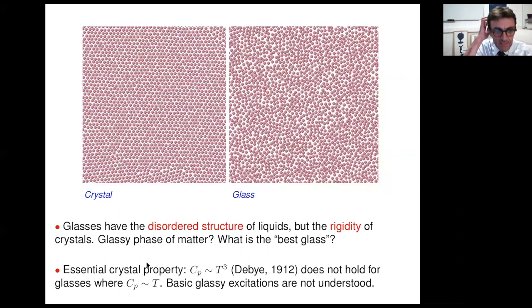So there are many physical properties of glasses that are surprisingly not well understood. So let me mention a shockingly simple one. Since the work of Debye and Einstein more than a century ago, we know that the basic excitations in a crystal are plane waves and they control all the thermal and mechanical properties at low temperatures in these systems. As a result, we understand, for instance, that the specific heat in a crystal increases as the cube of the temperature at low temperature. By contrast, it's been known since the 1970s that the specific heat of glasses doesn't follow the same law. It's linear in the temperature, but we only have a very crude and quite empirical explanation for this behavior. So overall, it means that even basic excitations in glasses are not well understood yet. And this is just one simple example of this type of property and questions that are not well understood.